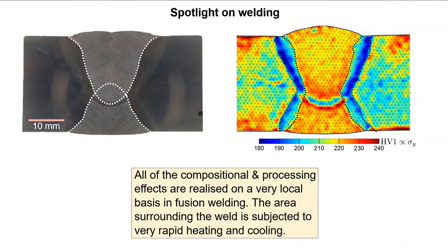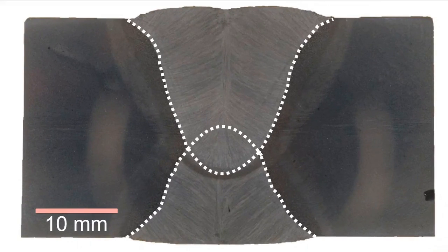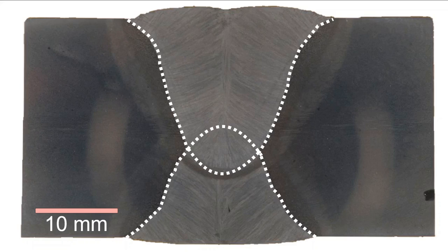It's not just the provision of the underlying material and what it is made up of which has an impact for its use — it's also subsequent processing. To sum things up for steels and bring back a few points of revision, let's look at this thick welded steel section plate. This plate was welded first on the bottom and then welded at the top using a process called sub-arc welding. The first weld has been remelted by the second, but the outlines of the fusion zone are pretty clear. Just outside these lines, the baseline microstructure has also been affected, as indicated with a slightly darker pattern highlighting the fusion zone. Some dendritic structure can also be observed in the fusion zone.